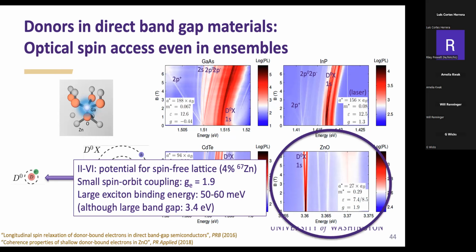Okay. We choose zinc oxide because it has the potential long-term to be a spin-free lattice. You can get rid of all the nuclear spin noise. It has small spin orbit coupling, which means longitudinal relaxation times of the spin should be very long. It has a large exciton binding energy, 50 to 60 millielectron volts, which is a consequence of a large band gap, which can be awkward to work with. We are working in the near ultraviolet.